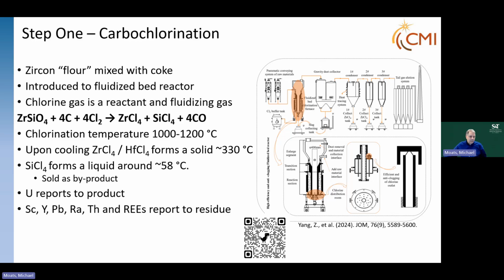So in carbochlorination, zircon flour is mixed with coke. It's introduced into a fluidized bed. Chlorine gas is the reactant and the fluidizing gas, and there's the reaction. The zirconium tetrachloride and the silicon tetrachloride are both gases. The chlorination temperature is between 1,000 and 1,200 degrees Celsius.